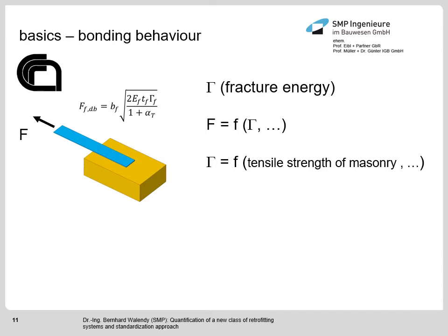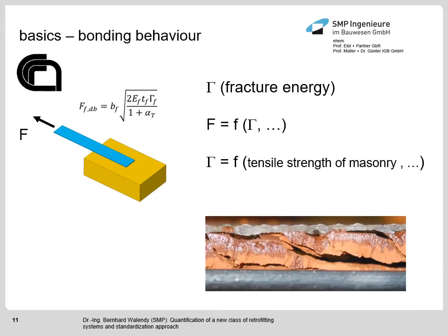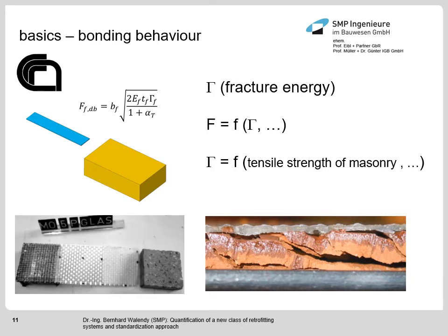As we remember, for epoxy-based systems, we have this very brittle cohesive failure. And for these systems, the national regulations work pretty well. But we remember, we have a very different material behavior for the seismic wallpaper. And the standard failure mode for the seismic wallpaper, as it is shown here, is not cohesive failure, it is an adhesive or a quasi-adhesive failure.